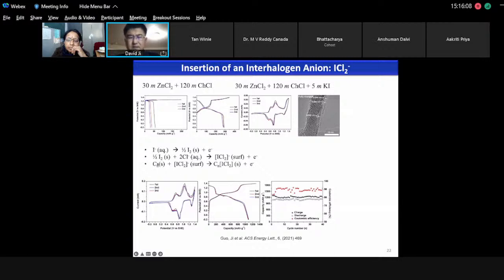So this reaction is going to be sensitive to, it's going to depend on the surface area. You probably can see that because you need a plating first. So we worked on an extremely high surface area material. The capacity is extremely high. It's 1100 milliampere hours per gram. This is probably the highest capacity electrode for anion storage.